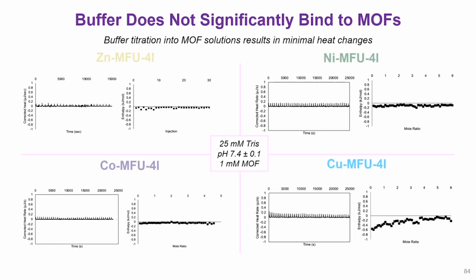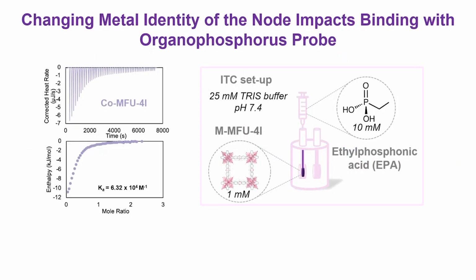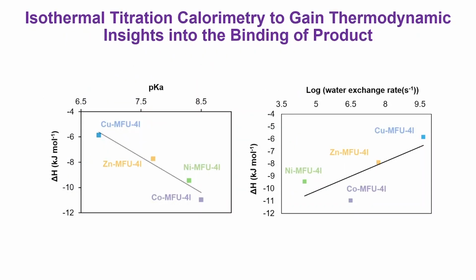There is nothing there. And now when we titrate our product to the material, you could see these beautiful curves, and we could extract heats really easily out of these materials. To cut to the chase, that's what you get. If you do a water exchange rate versus delta H, or a pKa versus delta H, you see different plots, but in different directions.